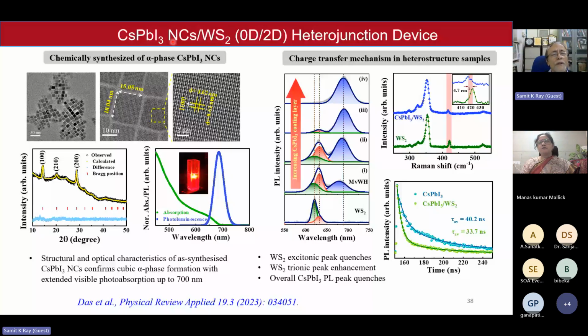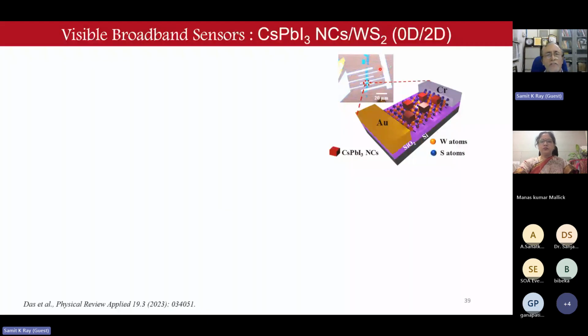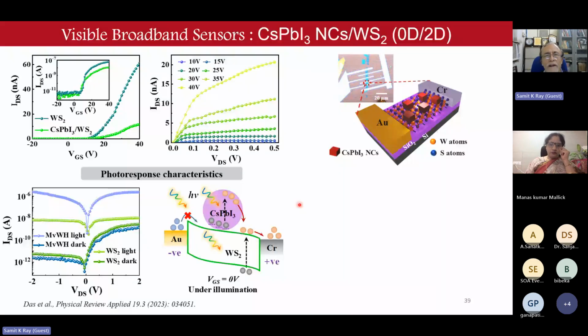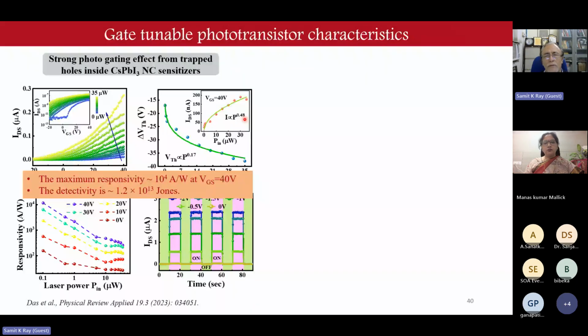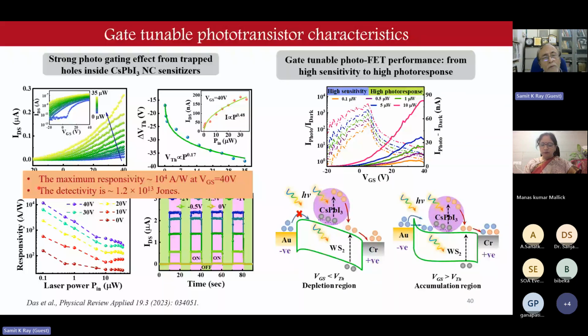So basically what we did, we made these perovskite nanocrystals and integrated them on some kind of 2D substrates, like tungsten sulfide, and made device structures. From there, again, we made transistors and found out the characteristics of the transistors and the devices we make. By doing this, we get a much, much higher responsivity, about 10 to the 4 ampere per watt. Earlier, I was talking about 5 ampere per watt to 50 ampere per watt.